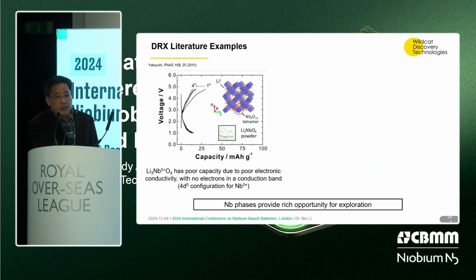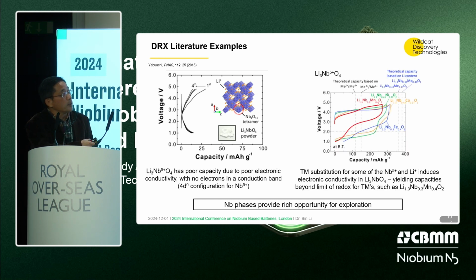And for the DRX, this material was discovered in 2015. This material started with niobium. Here you see this powder is white. It means it's a semiconductor. It's not conductive at all. But if you dope in this element, niobium, with different transition metals, here it's manganese, nickel, cobalt, and iron, you can almost dope in any transition metal in the periodic table. Literally. It's very rich chemistry. There's a lot of work that can be done.